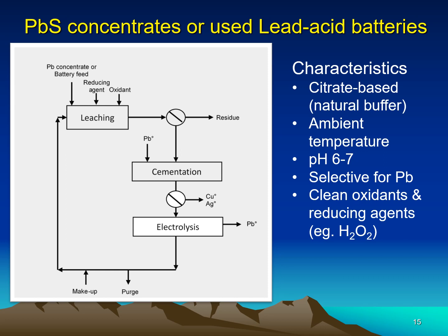The characteristics of this process are it's citrate based, and citrate is a natural buffer. So if the reactions need hydrogen or produce hydrogen, such as in electrolysis, the pH stays basically the same. It's at ambient temperature, pH 6 to 7, very selective for lead. In concentrates, we have other sulfides which at these conditions do not react or react very, very little. And also in the lead batteries, as the alloying metal, sometimes they have antimony, sometimes they have tin. We find that these are not leached in the citrate solution at these conditions.